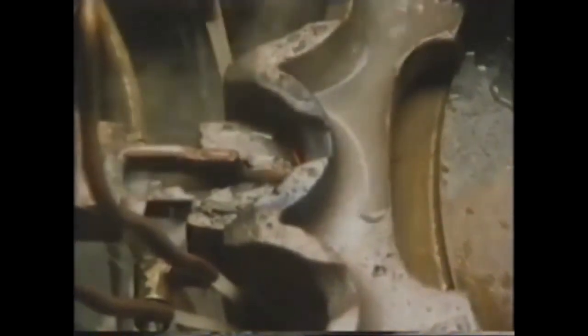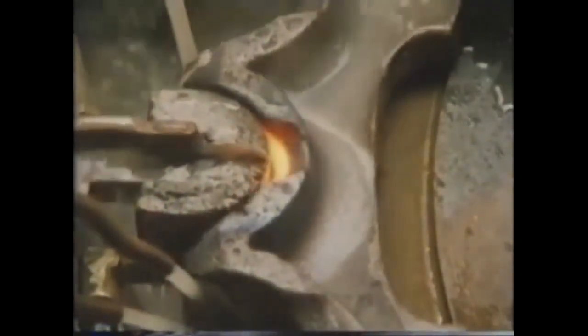Both induction and flame hardening produce high surface hardness on a particular part of a component, and there's less distortion than in furnace heating. A wide range of quenches can be used: water, oil, polyvinyl alcohols, and air blasts. But there are limitations. The components to be treated must be ferrous, and none of the methods are really suitable for very small pieces. In flame hardening and induction hardening, it's usual to follow the cycle by a low-temperature stress-relieving treatment.